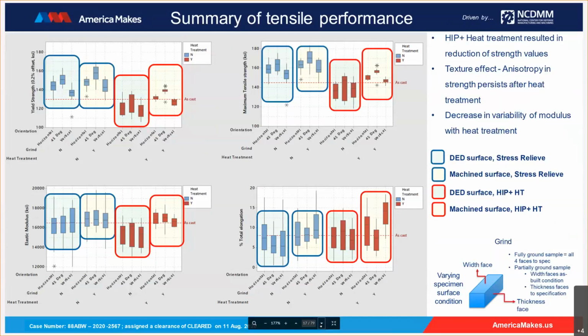So for example, here we have a summary plot showing the influence of heat treatment, specimen surface condition, and tensile test orientation for the wall features here. Some of the primary takeaways here is that heat treatment produced a significant difference in the strength performance. We've seen a decrease with the specific heat treatment we've performed on these specimens.